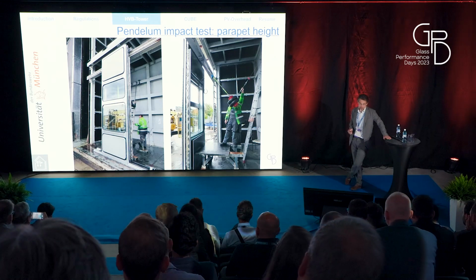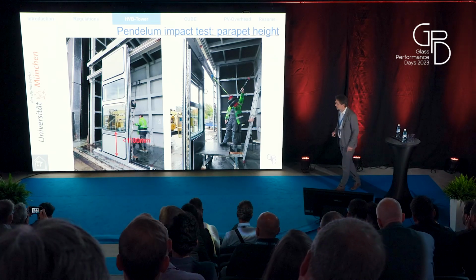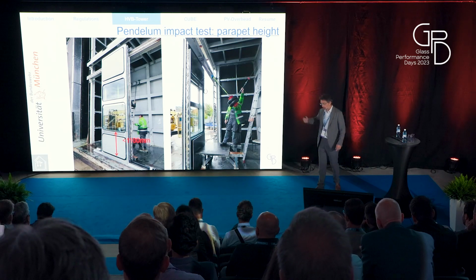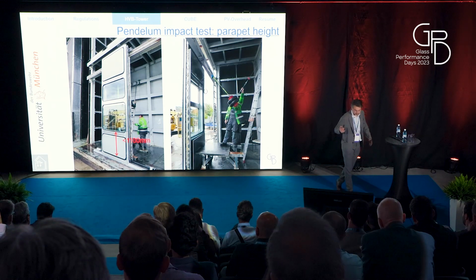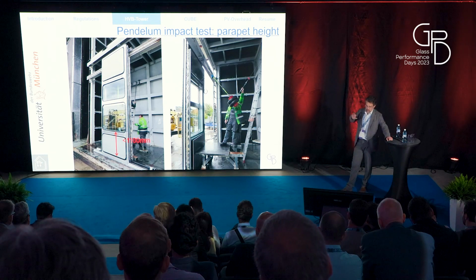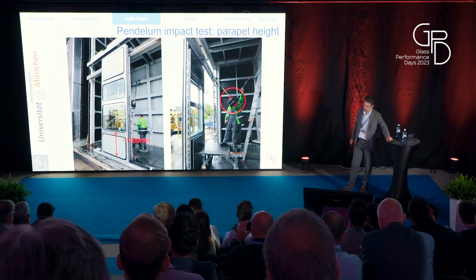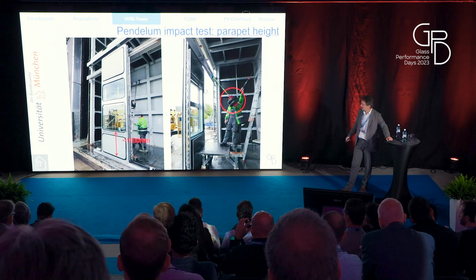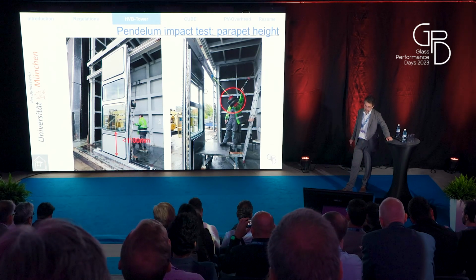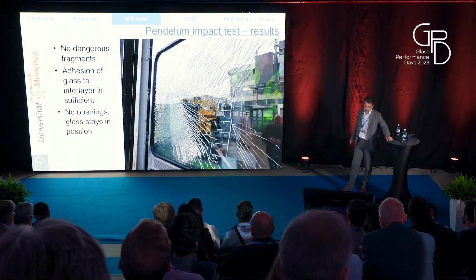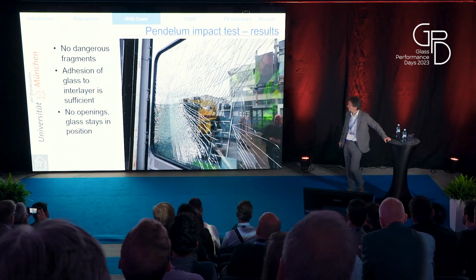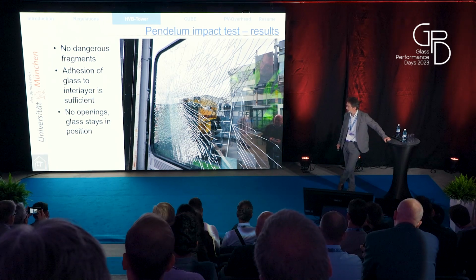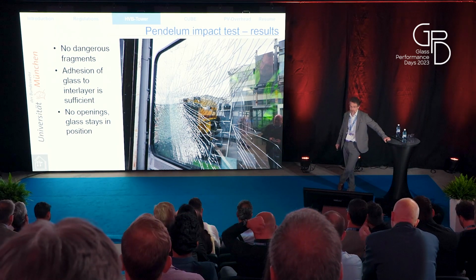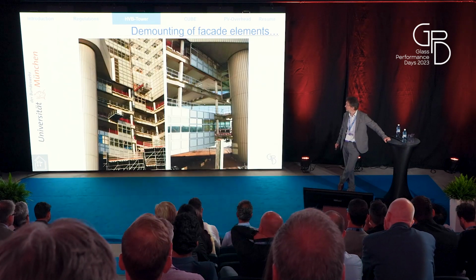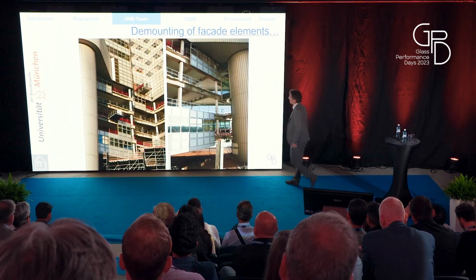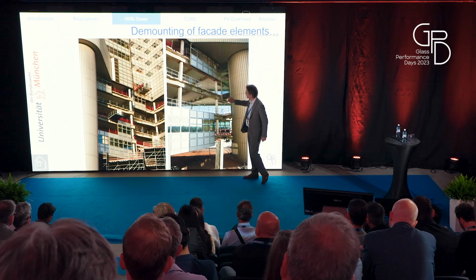We had to do a pendulum impact test because the parapet height was not high enough. So in case you open the window, the outer layer of the glass, the coated glass, has to be the anti-drop device. So we did a pendulum impact test to prove also this additional requirement. And the result was, of course, no dangerous fragments, adhesion is sufficient, no openings, glass stays in position, so everything's fine, and we can continue. This is an element we will look just 3 slides later.